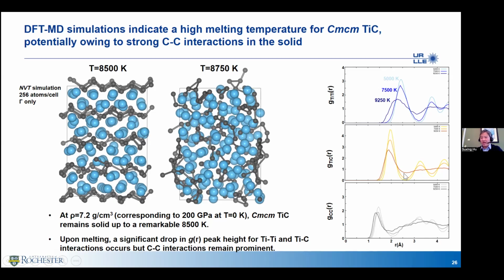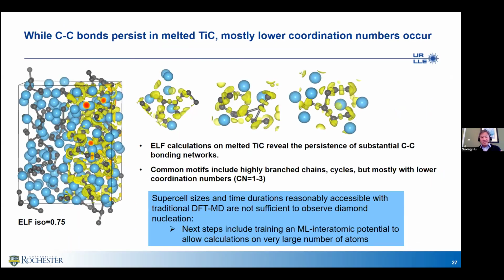The titanium-carbon pair correlation function also washes out here. But if you look at carbon, first of all, this peak does not move much, and the magnitude does not change much. That already tells you this carbon chain is still persistent in such a melting system. So this is an interesting system. First of all, it's hard to melt, and even when it's melting, the carbon chain still persists. Of course, when you just do such a direct QMD calculation, it's still very hard to really identify if a diamond can form because the whole system is so small.